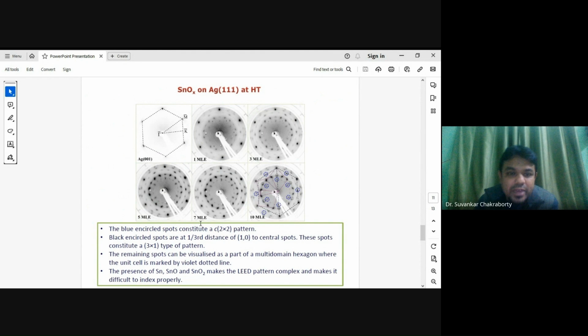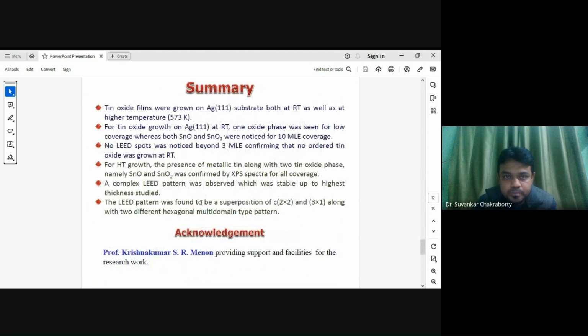these three present there. So in summary, we can say tin oxide was grown on Ag(111) at room temperature as well as high temperature. For room temperature, only one oxide phase was seen for low coverage, whereas both SnO and SnO2 are noticed for 10 monolayer coverage. No LEED spots were noticed beyond 3 monolayer, confirming that no ordered oxide was grown at room temperature. For high temperature growth, the presence of metallic tin along with two oxide phases was confirmed by XPS. A complex LEED pattern was found where we see c(2x2) and 3x1 patterns.